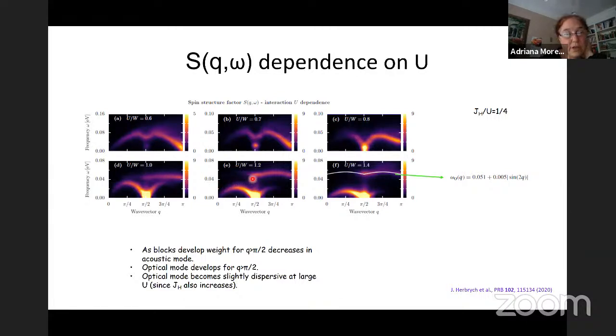Eventually, as U continues to increase, because this is kept constant, J Hund also increases, and you see how the optical mode goes up, while the amplitude of the acoustic mode goes down. This could be related to the fact that the acoustic mode is ruled by an effective J that should go like 1 over U.